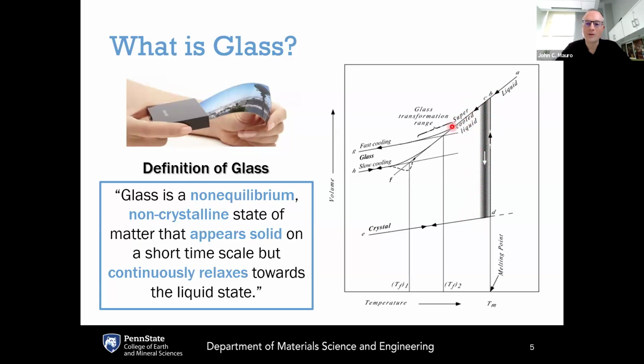Now, if you take this supercooled liquid and you continue to cool it, as the supercooled liquid continues to cool, the viscosity is getting orders of magnitude higher, meaning that the atomic motions are becoming slower and slower and slower. Eventually, those atomic motions become slow compared to the observation timescale on which you're observing the system. And when that happens, you undergo this continuous, what's called the glass transformation or glass transition process, which is a kinetic freezing in process because you're observing the system on a timescale that's becoming slower than the timescale of the actual kinetics of the supercooled liquid.